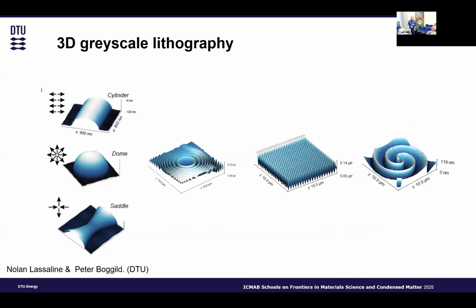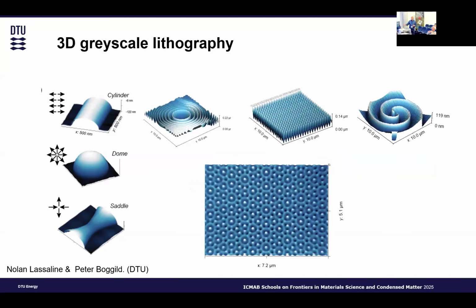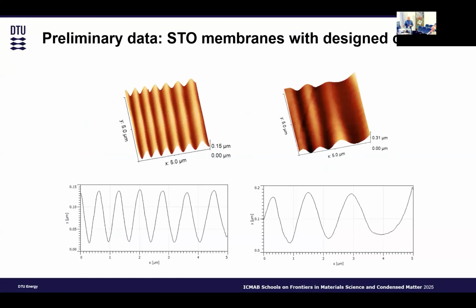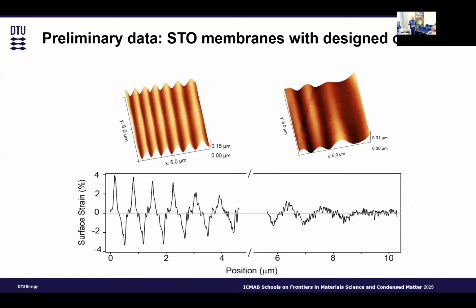So what we did, you can do some other things. So these are real samples that we made. And this is a quasi-crystal that we can also do. So basically what we did, we put the membrane on top of the material. We can see that it conforms. We can measure the amplitude. Everything looks the same, so it's conformed really well along the material. What was more interesting was to measure the strain on the material. And here we can get 4% strain. And 4% strain is a little bit more promising.